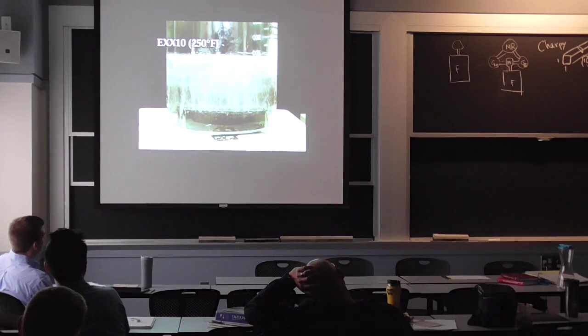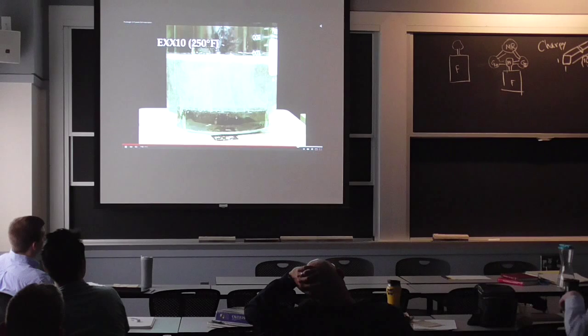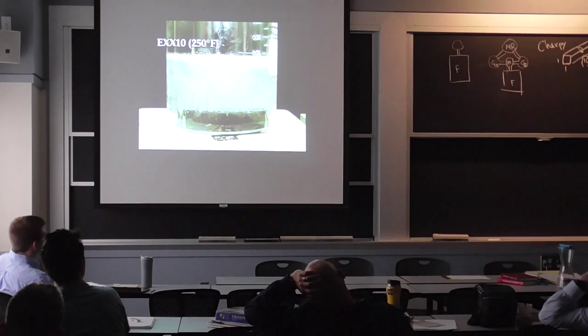When it is placed into mineral oil that is heated to 250 degrees Fahrenheit, the temperature that we showed allows hydrogen to diffuse 1,000 times faster than room temperature. We can see that diffusion begins again, and a rapid release of hydrogen occurs. Therefore, welds that are preheated and allowed to slow cool or post-heated will allow more hydrogen to diffuse, reducing susceptibility to hydrogen cracking.